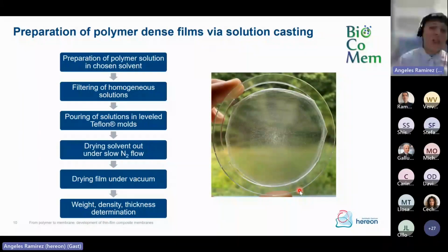Now, before we start testing our polymer as we receive it, and as I mentioned before, we need to prepare dense films. To do this, we need to choose the right solvent for the polymer, that is the one that gives us a homogeneous solution. And then we need to filter the solution in order to eliminate any impurity that will affect the measurement. Then we pour this homogeneous solution into leveled Teflon molds, and we apply a constant nitrogen flow in order to have a regular solvent evaporation, and also to keep the polymer at the most equilibrated state for the film formation. When the weight of the film is constant, we proceed to dry this film in a vacuum chamber to eliminate all solvent traces. And then we proceed to measure, for example, density, and most importantly, the thickness of the film.